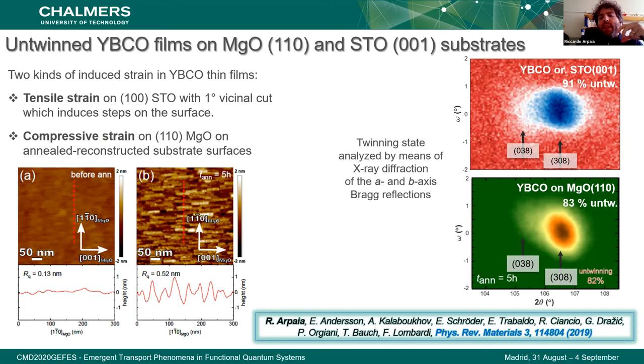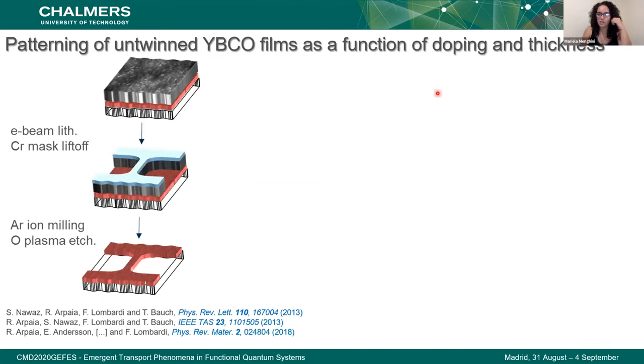Here basically we see in the plane the presence along one direction of both the A and B axis, and that is given basically by the presence of two peaks, the 308 and the 038 peak. And what happens is that basically in one direction we only see one peak, because only one axis is present in any direction, because the film is untwinned. And we got untwinning percentages between 80 and 90 percent and beyond, which are the best achieved so far in YBCO thin films.